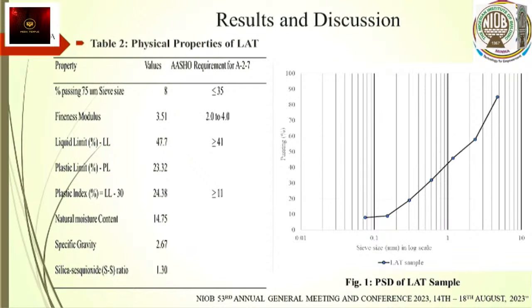The fineness modulus was found out to be 3.51, and the code requirement says between 2 to 4.0. So we felt it fits in. Then the liquid limit was 47.7, and the code says it must be greater than 41. We had a plastic limit of 23.32, plastic index of 24.38, and the code says it must be greater than 11. The moisture content was 14.75, specific gravity 2.67, and silica sesquioxide ratio 1.3. You could see the plot of the particle size distribution for the laterite as shown.